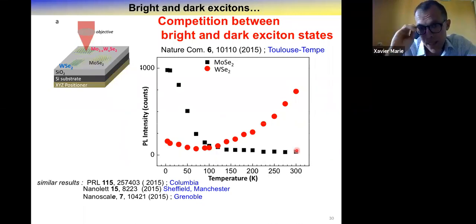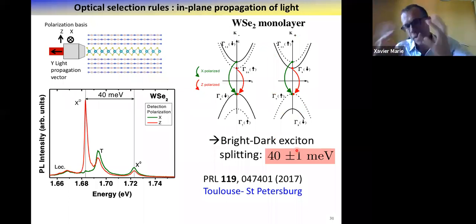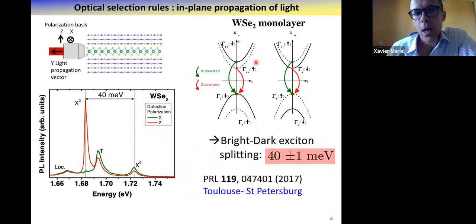What we did is we came back more on the symmetry of the system and the symmetry of the wave function. And if you look now a little bit more in detail at the recombination between the conduction state and the valence state, so far I told you that what is allowed is a green, represented by the green arrow, which is a bright exciton, which corresponds to in-plane polarized light.